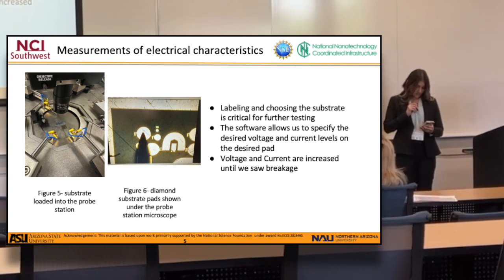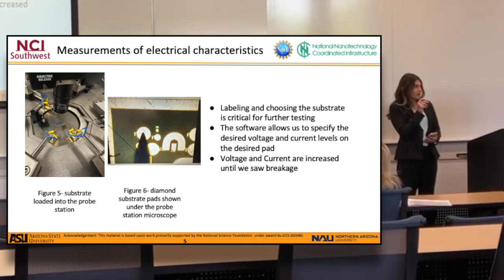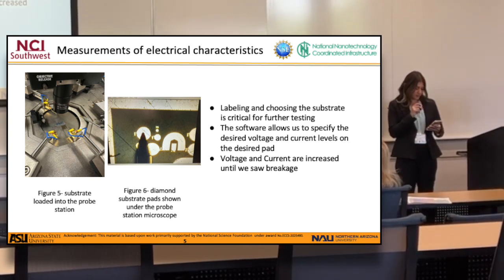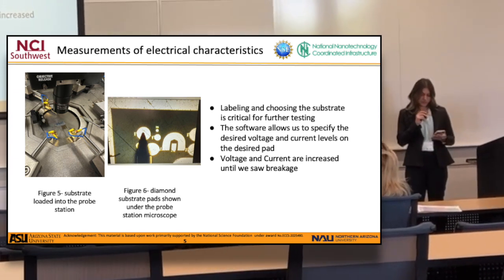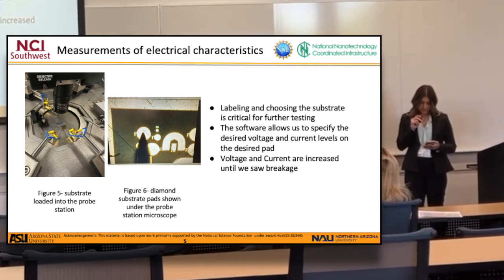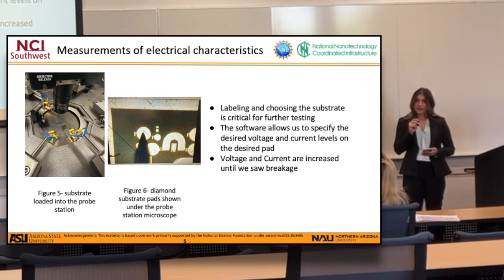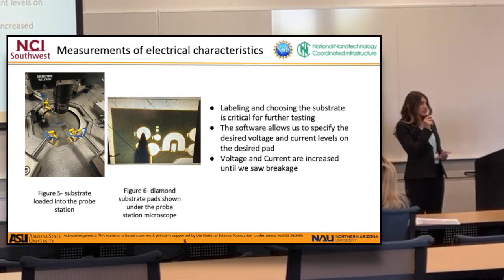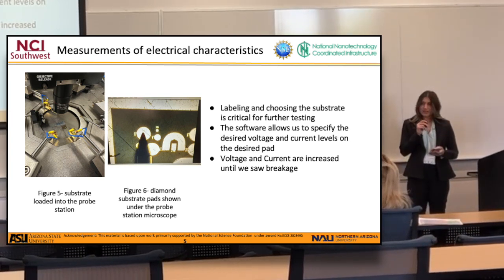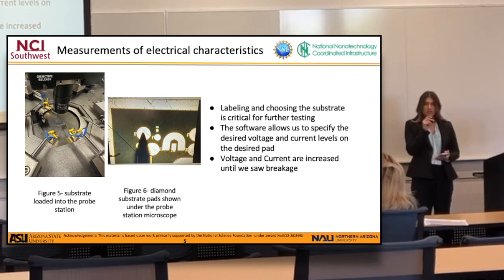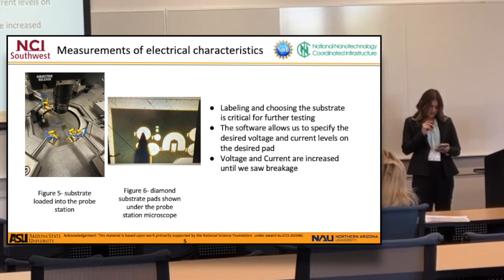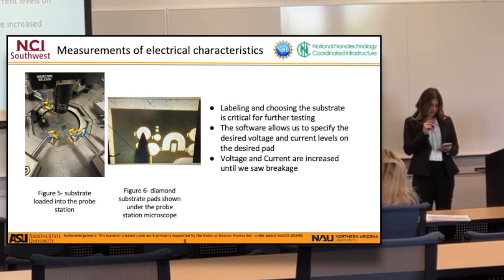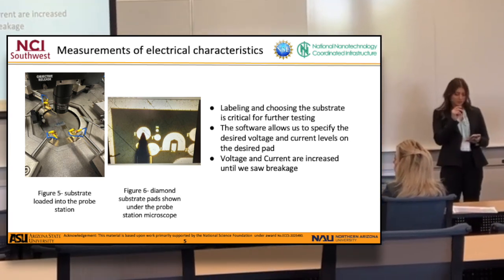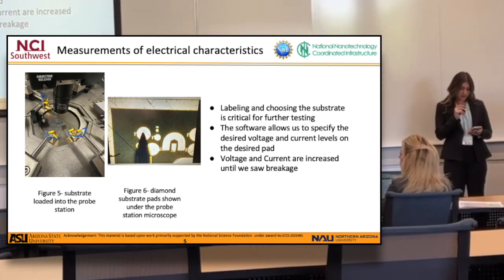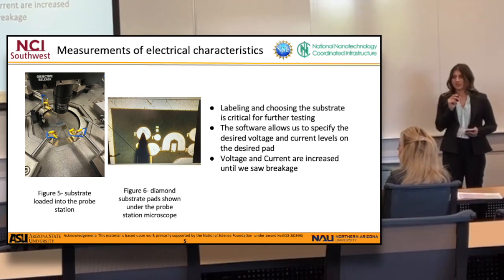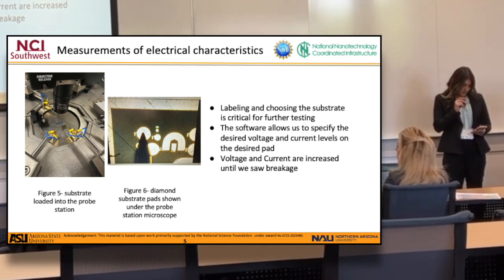And then this was the procedure that we followed to measure our sample. First, we identified the microscope images of our patterns and labeled the pads for easy identification during testing. And pads are the gold-looking circles shown in Figure 6. As you can see, there are various shapes and sizes, but we chose to take measurements of the circle-shaped ones because their area is easy to take, and that is important during graphing and analysis.